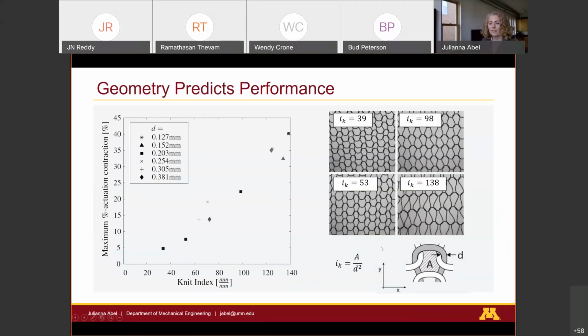But we've done this for a lot of different samples, and we've been able to characterize and create macroscale relationships. So we've identified this knit index parameter. It's the ratio of the area over the diameter of the wire squared, and that really governs the maximum actuation contraction we can get from a structure. We found this very useful for designing applications. And you can see the different knit index. When you have a low number, it's a more densely knitted structure. The higher the number, the more open and porous that structure is. And so the more open and porous it is, the more actuation contraction you're going to get from it.